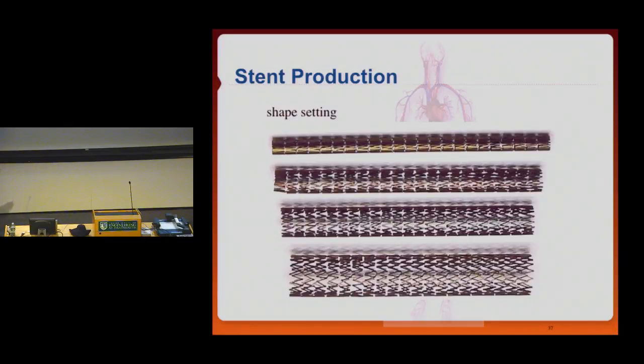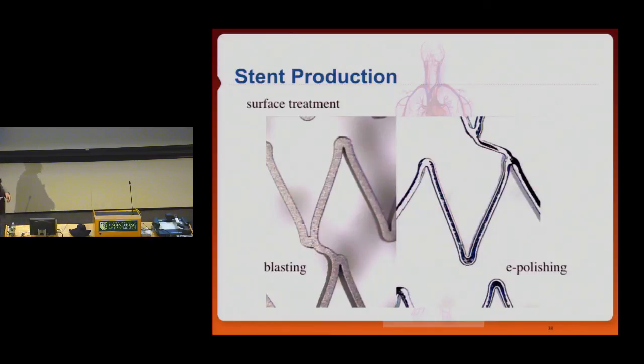After laser cutting, what you do is push a tapered mandrel through this thing and do a heat treatment, and that locks the bigger shape in place. And depending on the final size of the product, you have to do that multiple times, so you can't go from the as cut to the finished size because that would put too much strain on the material. So you do that in 2 or 3 steps, and do a heat treatment, 500 degrees or something like that. That locks the shape in, and it also creates the right transformation temperature. So we have ways to adjust that up and down a little bit through heat treatments. And then obviously the surface treatment is very important. The stent is first blasted with little glass beads or whatever it is, and then electropolished, and the final product has a fabulous surface.